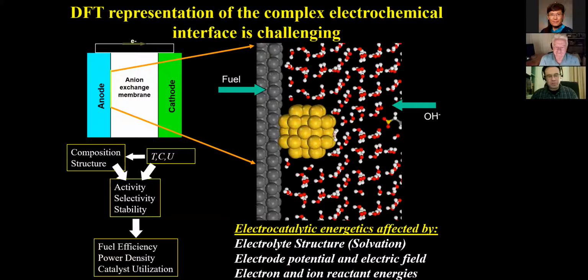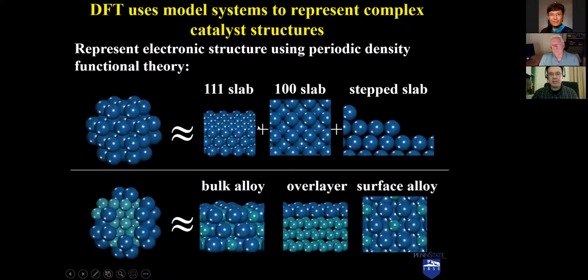Now, making reduced models is true in any heterogeneous catalysis application. Even if this was in contact with a gas phase and we knew it was neutral and not electrified, and we were willing to neglect the support, even the particle itself is going to be challenging if it's on the size of nanometers. But there's a lot of established work, both experimentally and computationally, to make model systems. Right? We're relatively comfortable modeling a nanoparticle as kind of like an extended surface. Maybe that top surface is a 1-1-1 extended surface because it's hexagonally arranged metal atoms. Here we've got squares, that's like a 1-0-0 surface, and then we've got a step between them.